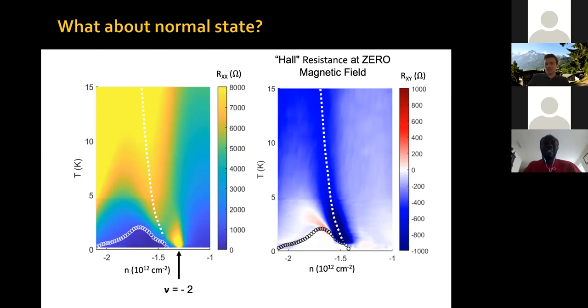in that same region, we measure a finite transverse resistance, okay? Whereas everywhere else, the transverse resistance is almost zero, okay? Here you see there's almost no signal. Here there's little signal, but here there's this big signal, look for deep dark colors, right? This is dark blue.